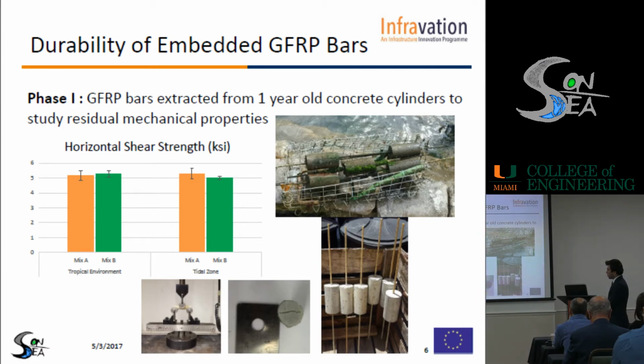In the tidal zone, the results are still comparable. You can see that both of them are above 5 KSI. So they are still comparable. And after a year embedded in seawater concrete, you can see that we don't see any difference between mix A and mix B. So the seawater concrete does not have a significant effect on your GFRP durability after a year.